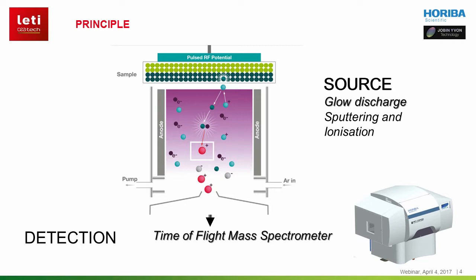The diameter of the cylindrical anode defines the probing area. 4 mm anodes are typically used, leading to 4 mm diameter craters. Such plasma works at a few millibars and the energy of the ions in the plasma is about 50 eV. The low energy minimizes surface damage and high current ensures high sputtering rates, as high as a few tens of nanometers per second.